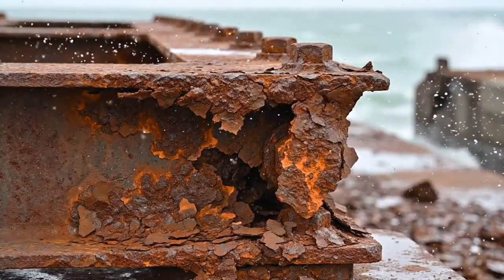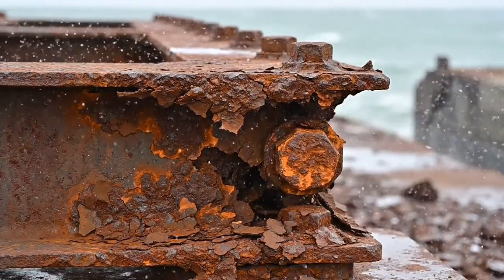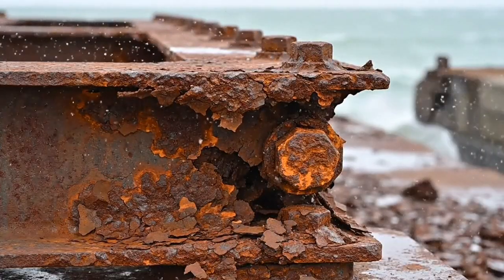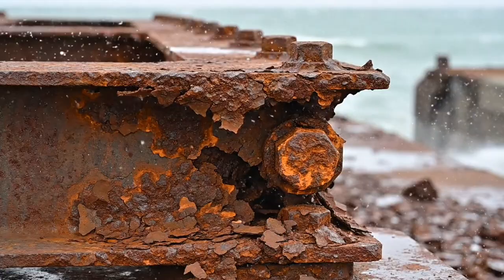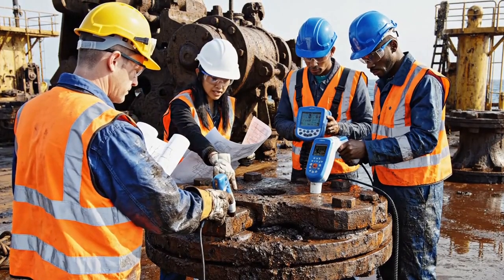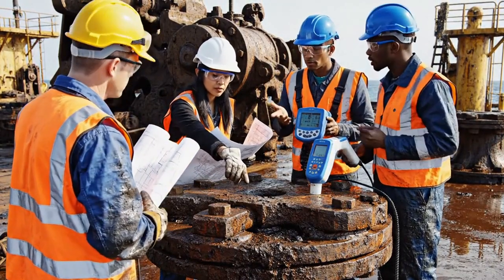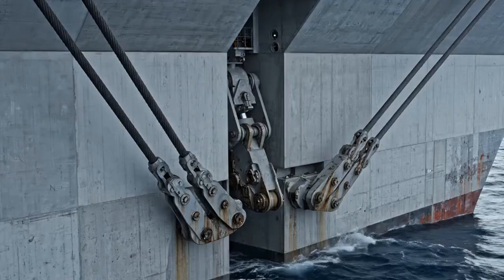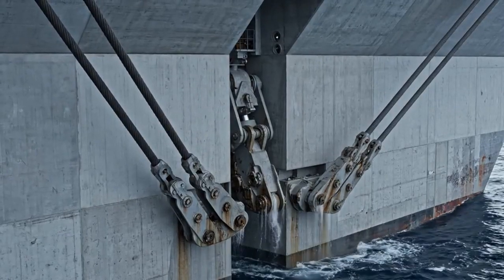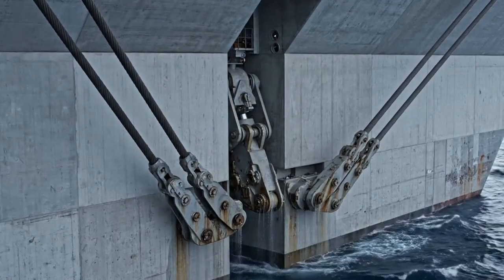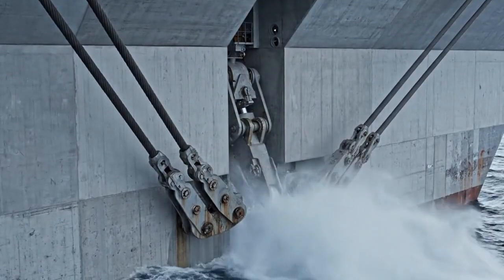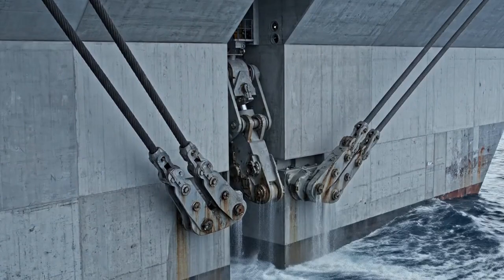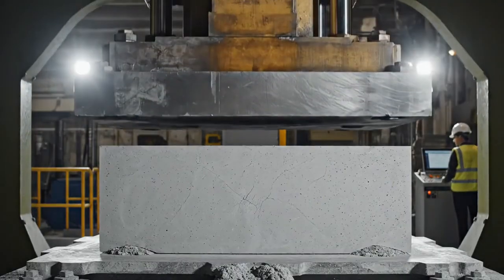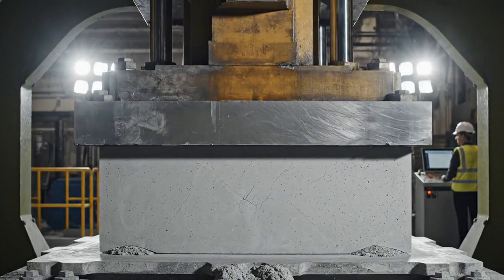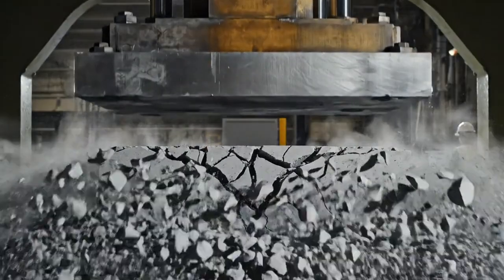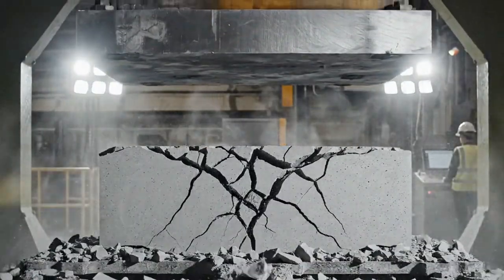Constructing a continuous 4-kilometer barrier in a highly corrosive marine environment renders standard structural carbon steel virtually obsolete. The saltwater corrosion rate would severely degrade the structural integrity within a single decade. Therefore, the primary building material engineered for this hull is marine-grade ultra-high-performance concrete, or UHPC. This is not your standard construction material. UHPC boasts a compressive strength exceeding 150 megapascals.